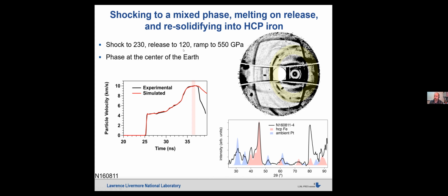You release to 120 GPa. That means now you're releasing to a completely molten state. And then we ramped back up to 550 GPa, and then we pulsed it with X-ray diffraction. And so what we did observe was solidification into the HCP structure. So this is a bit textured, but you can see the HCP triplet in the raw data.